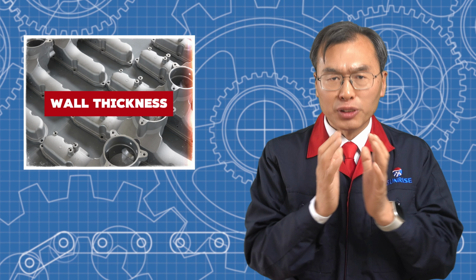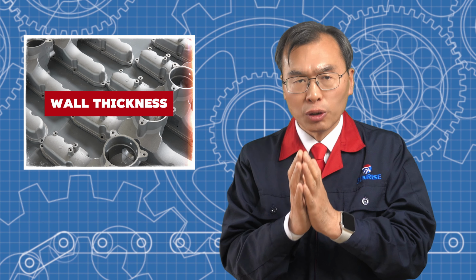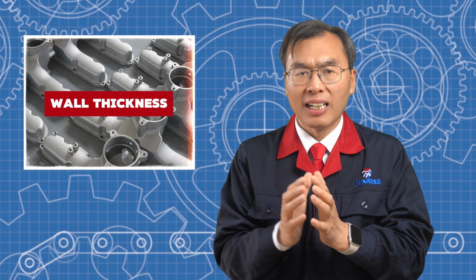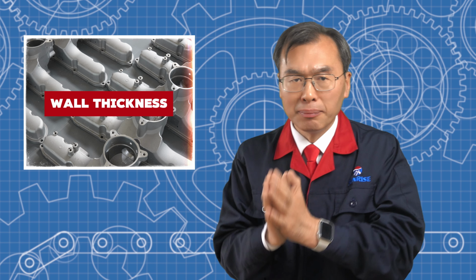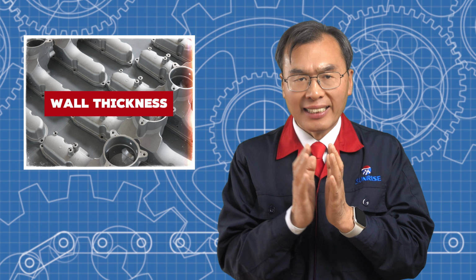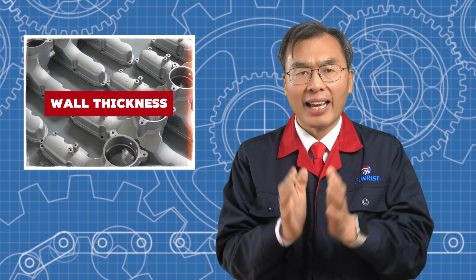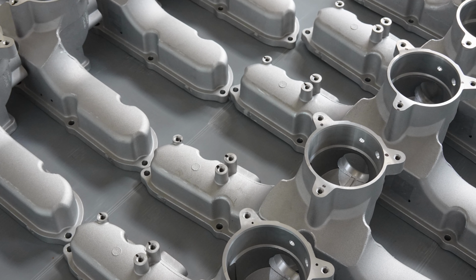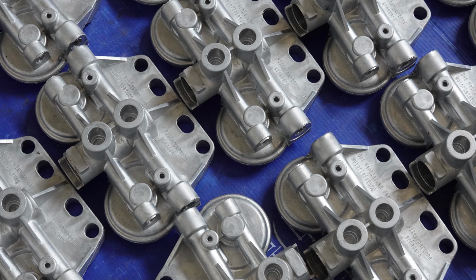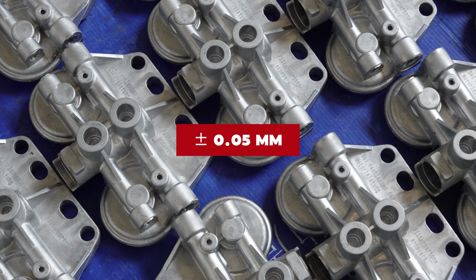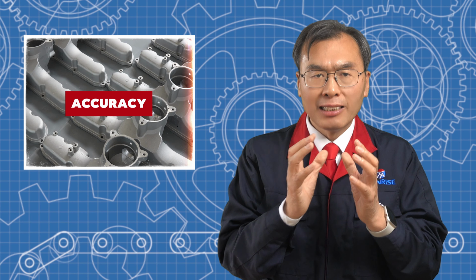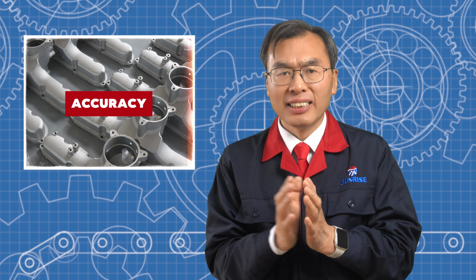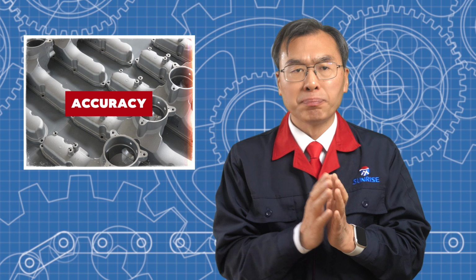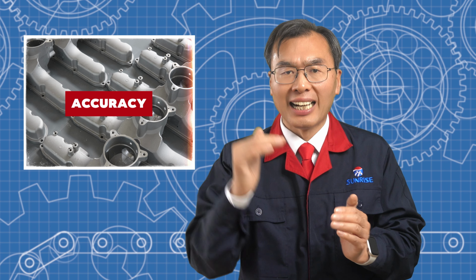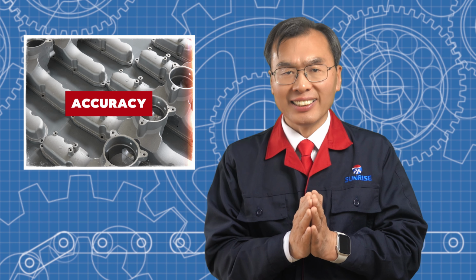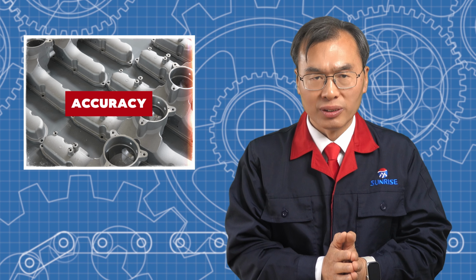High-pressure die casting can produce parts as thin as 0.5 mm, but most are between 1 to 3 mm thick. The final thickness depends on the alloy, mold design, and process control. High-pressure die-cast parts can have tolerance as tight as plus or minus 0.05 mm. Some very precise parts may need extra machining after casting. To get accurate parts, producers need precise molds, stable casting conditions, and good cooling control.